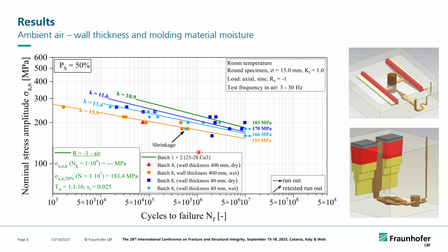Besides the pure wall thickness comparison, we also made a comparison with the wet and the dry molding material. As I said, the humidity is in the molding material, which is mostly sand. It is a bit a matter of CO2 emissions, because when I need to dry the mold before I go to a casting process, I will have to spend more energy in the production process. Why do we do this? Usually because the water inside the molding material will act as a hydrogen promoter, and together with the contact of the molten metal with the wet molding material, we propose that there will be more pores.